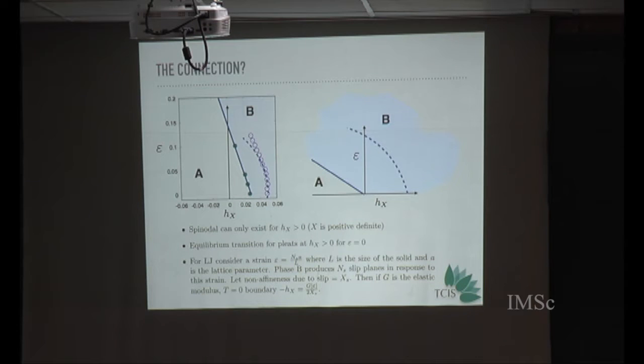And this connection becomes more obvious if you look at the phase diagram. So here is the phase diagram for the network. A is the unpleated phase, B is the pleated phase. This is the equilibrium phase transition line, and this is the dynamical line. You can argue that whatever be the interactions, this point has to be for positive h. So this dynamical line, the location can be different, but it always has to be at positive h. The equilibrium line can be anywhere because it depends on the free energies.